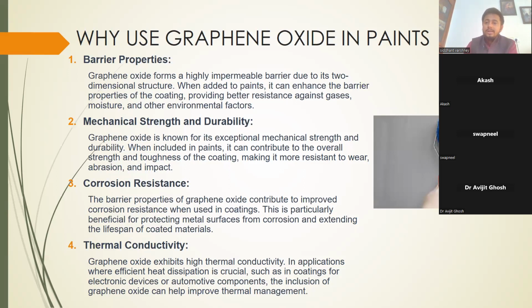Mechanical strength and durability: it improves the mechanical strength by 300%, as I already told you, by just including 1 weight% of graphene in the matrix. Durability, it is highly durable, and the loadings that I'm talking about in any application go from 0.3 weight% to a maximum of 3 weight%. Nowhere is it used beyond 3 weight%, except in very few applications. So we are just playing between 0.3 and 3 weight%.